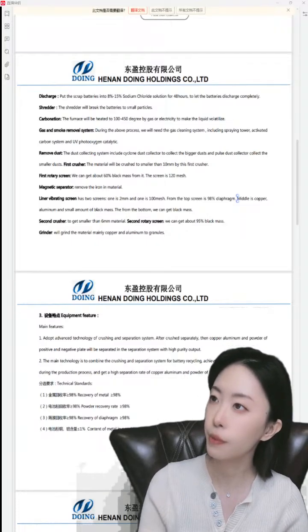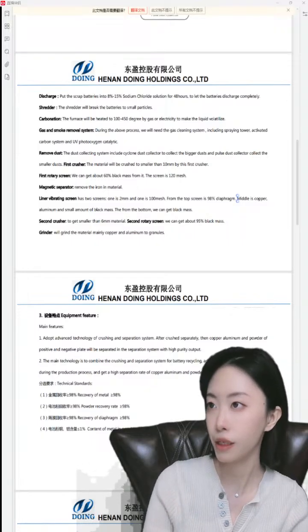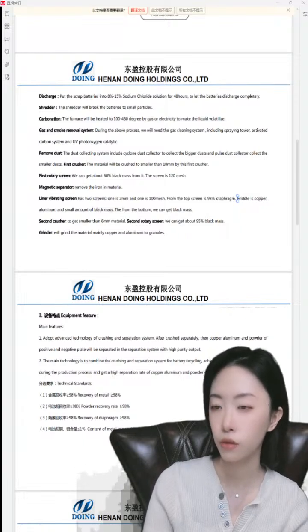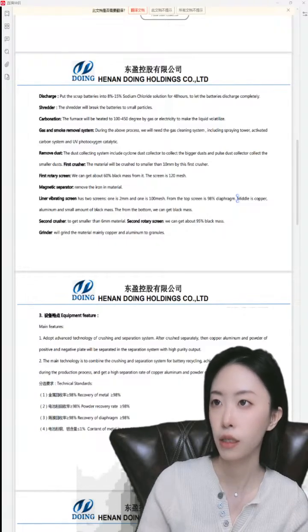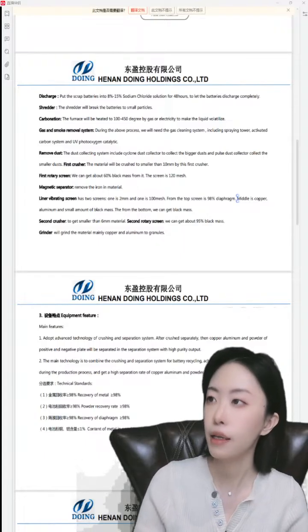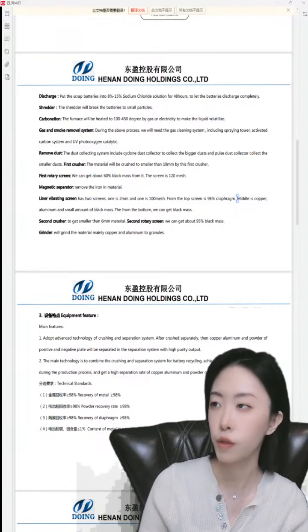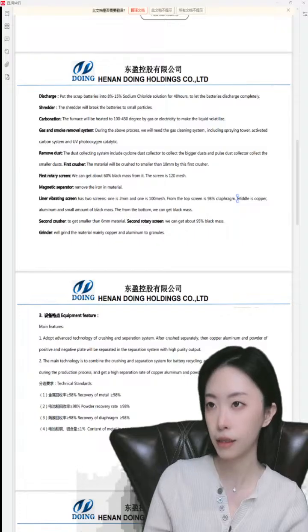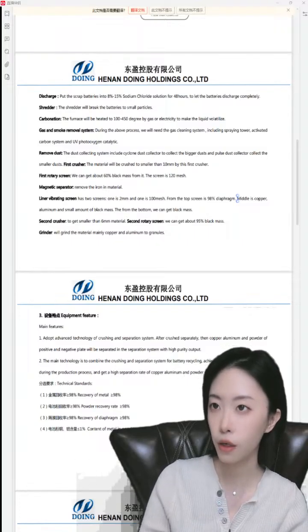Then we will use the shredder. This is a pre-processing step, and the shredder will break the battery into smaller pieces, nearly 2 to 5 centimeter. And then there's the carbonization system. The furnace will be heated to 130 to 450 degrees by gas or electricity to make the liquid volatilize. And then the carbonization machine or the drying machine is equipped with a gas and smoke removal system. During the above process, we will need the gas cleaning system, including spraying tower, activated carbon system, and UV photooxygen catalytic.